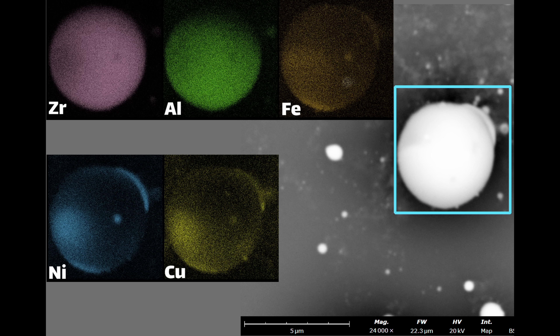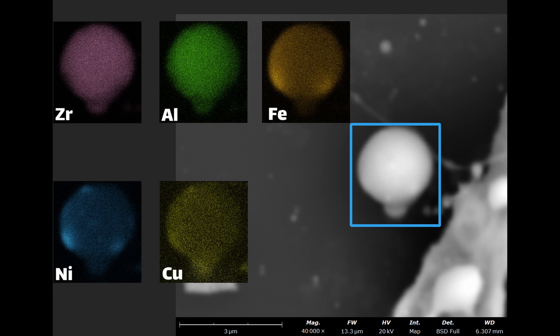Here is a reasonably decent result. You can see that the nickel and copper still kind of separated into their own phases, but are more evenly distributed across the whole particle. And this one is even better: the nickel has some hot spots showing it's starting to separate, but there's a nice background of both nickel and copper across the whole thing. The aluminum and zirconium don't seem to be separated at all, and the iron is also a pretty consistent background.